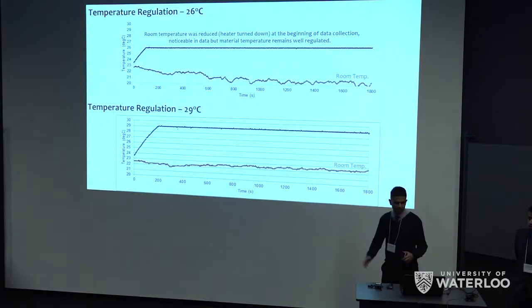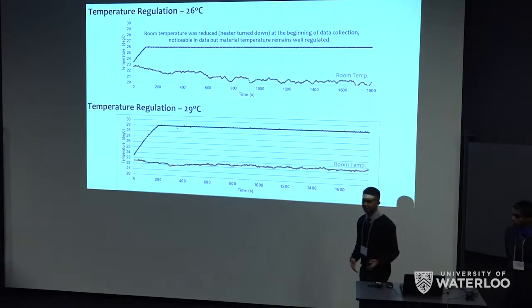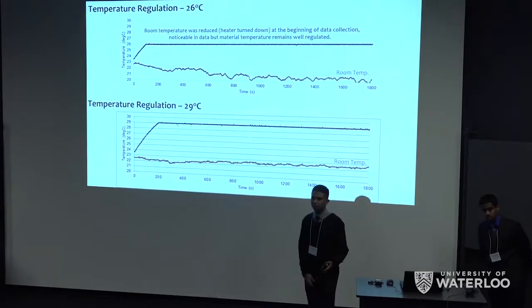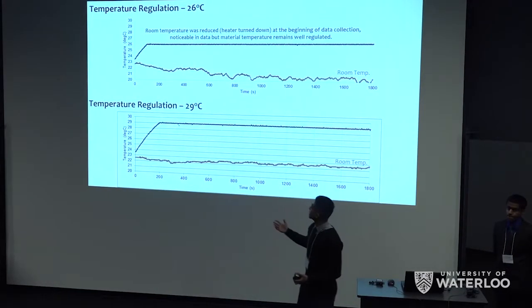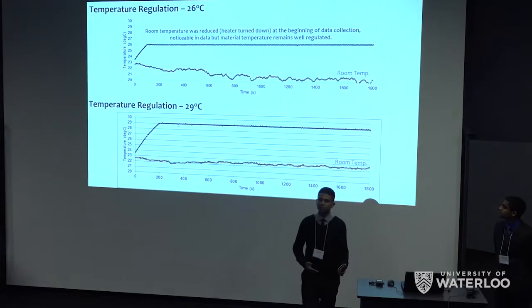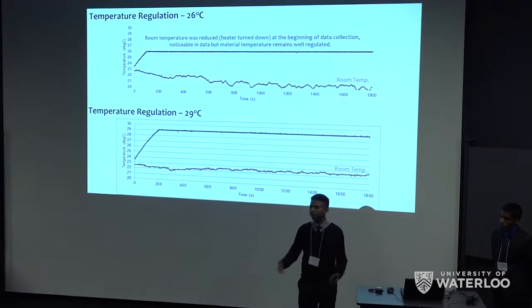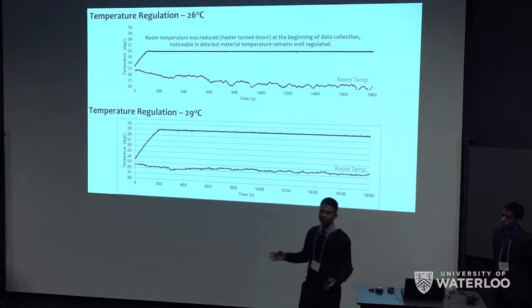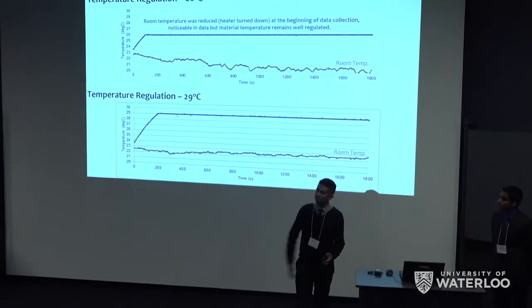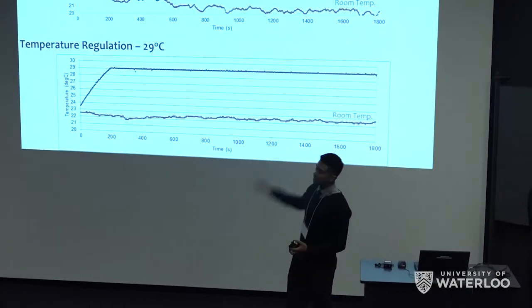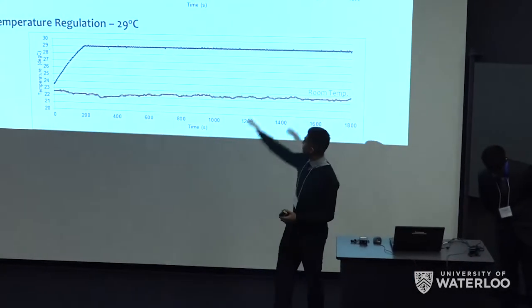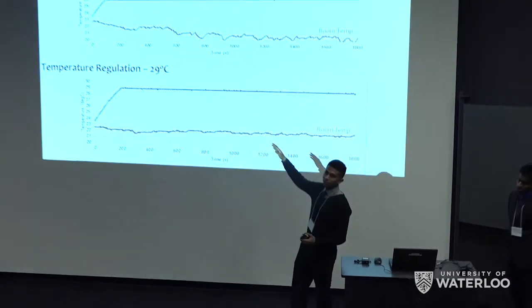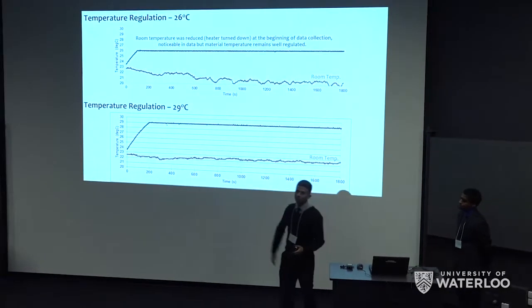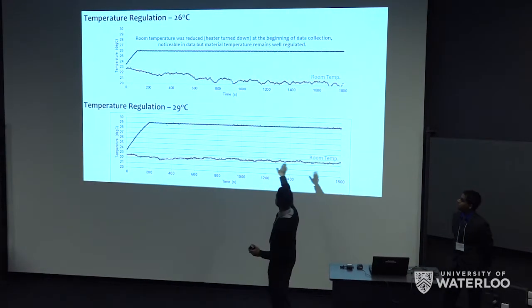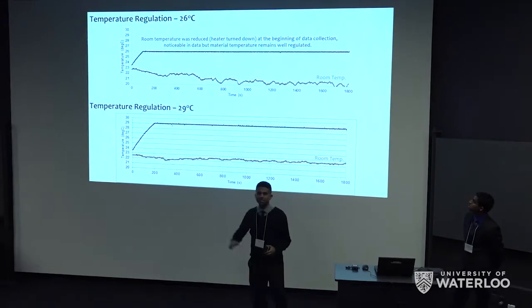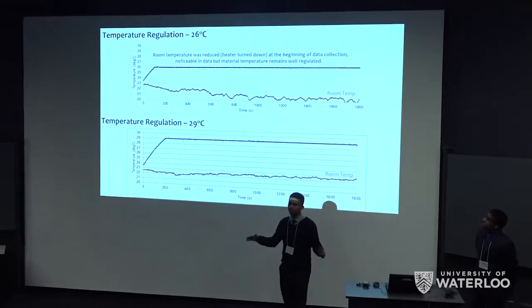So what I touched on earlier was temperature regulation, and here's some data that we collected using our regulation circuit. In the top, you can see that the user sets a comfortable temperature of 29 degrees Celsius. So we're going to ramp up the temperature until we hit that set value, and then we're just going to hover around there. You can see that we're pretty much constant at 29 degrees Celsius, despite rapid fluctuations in the room temperature that you can see below. Even though the room temperature has been dropping quite significantly, you can see that the temperature in our material is able to hold steady.